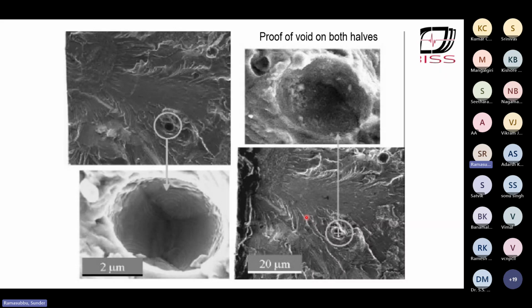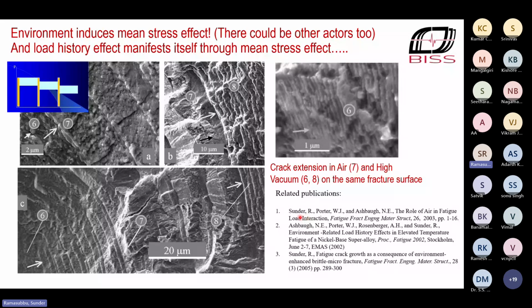So after a lot of, shall we call it PR and administrative effort, I was able to get on to a high vacuum test machine, a test system at the Air Force Research Lab in the US. And we did a test on a notched coupon, applying a number of blocks in air and then evacuating the chamber and going back and repeating another n blocks in high vacuum. And we had to wait 2 days to get 10 to the power of minus 8 torr vacuum, because my other colleague, Andrew Rosenberger, who afterwards really helped with the standard itself, he said that anything less than 10 to the power of minus 8 will not do. There will always be even a ppm level of moisture that is good enough to cause an environmental effect.